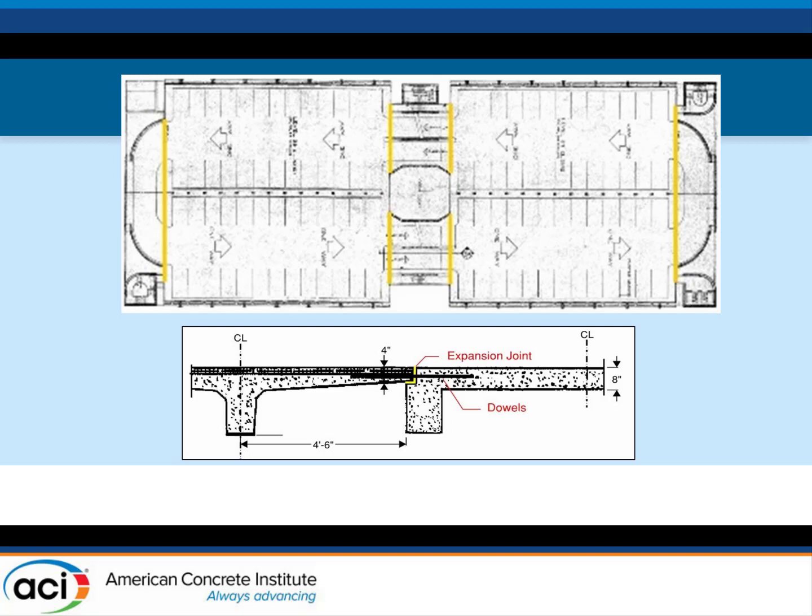So needless to say, the water got in the yellow joints there, corroded the steel. One engineer came along and started cutting all the reinforcing, not really paying attention to the fact that they were just trying to free the garage up to move even more so. So, needless to say.